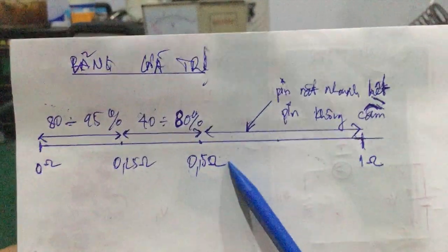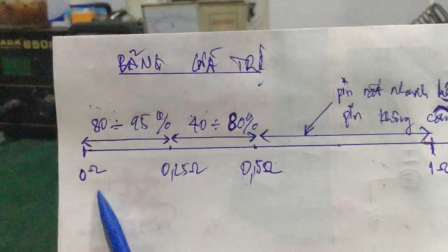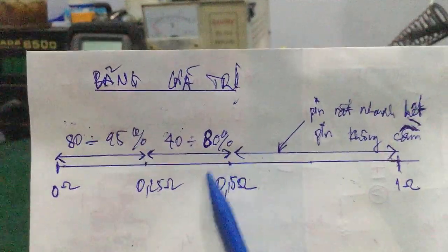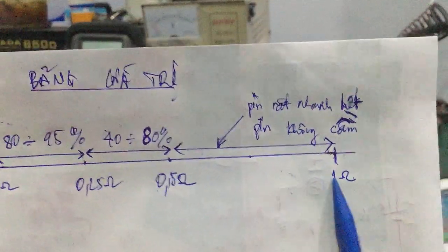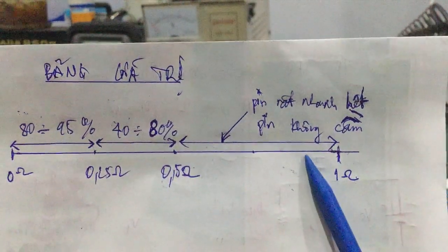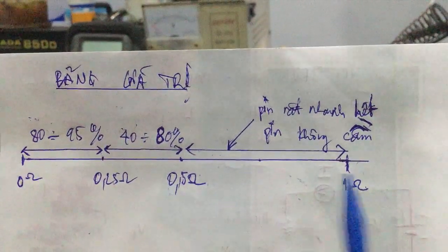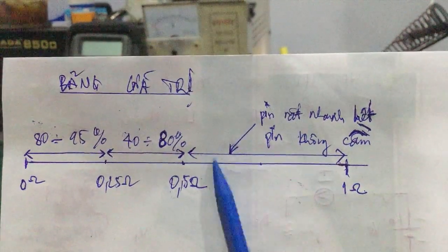Lúc đầu mua pin thì nội trở thấp, nhưng càng về sau nội trở sẽ tăng lên đến 1 ohm. Trong khoảng này pin của mình rất nhanh hết pin, không cầm, không giữ được pin nhiều. Phạm vi từ 0.5 ohm đến 1 ohm thì các bạn nên thay pin mới. Tại vì nội trở hạn chế khả năng nạp, làm giảm nhanh điện áp của pin khi có tải và rất mau hết pin.